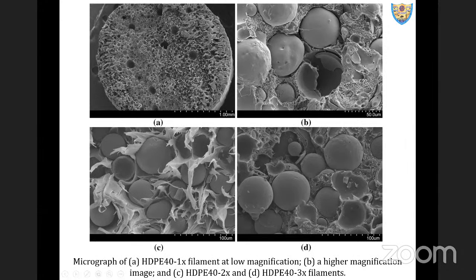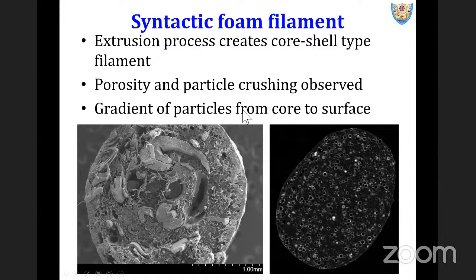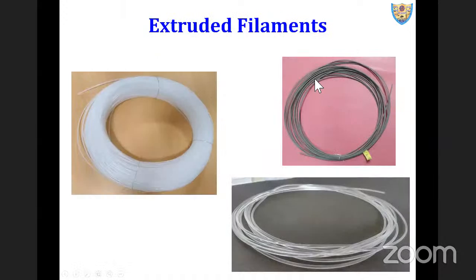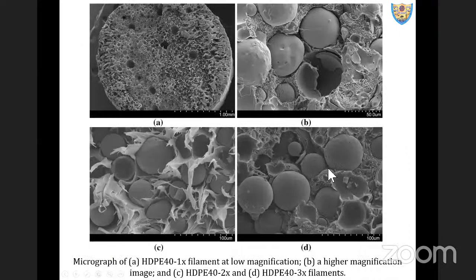This is 40 by weight in HDPE matrix, this filament, 1 time extruded. 1x means 1 time extruded. 2x is this: the 1 time extruded filament, we chopped it again, pelletized it again, and again extruded, and that becomes 2x here. And one more cycle, 3x. Now 1x, 2x, and 3x, we did that to check the recyclability potential of the developed filament, number one, and to check how many micro balloons have survived, so that we can have that syntactic foam or lightweight effect.